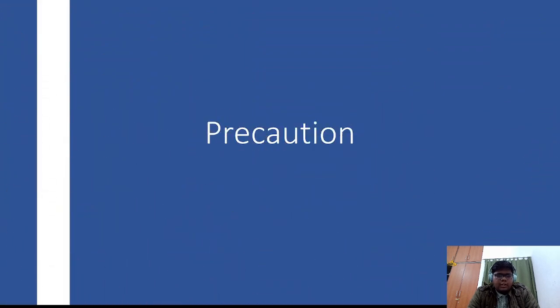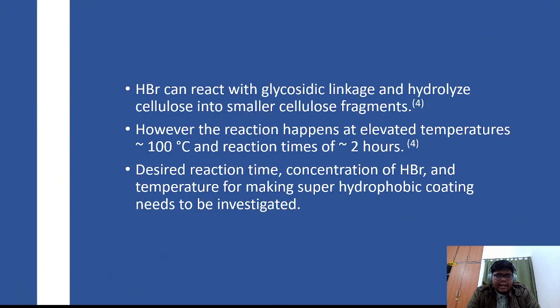There is an important precaution that we need to take, which is that HBr can react with glycosidic linkage of cellulose and hydrolyze it into smaller cellulose fragments. However, this reaction happens at elevated temperatures of around 100 degrees Celsius and reaction times of 2 to 4 hours. Desired reaction time and concentration of HBr and temperature for making super hydrophobic coating needs to be investigated. We will have to keep our temperature and reaction time less than this so that only the surface of the cotton gets reacted with HBr and the bulk of cotton fiber is not affected by it, thus retaining the strength.